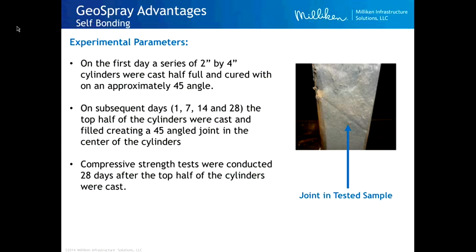Another advantage of this material is the fact that it is a highly reactive material, so it will rebond with itself. And when we're lining a pipe, the question was asked earlier, what is your typical thickness? Usually it's 1.5 to 2 inches. When we're going through and putting in a lining, we usually will do a 3/4 inch thick lining. Let that set up, and this material does set up very quickly. It sets up in 3 hours. Let that set up, and then if we have to do, we come through with our second pass.